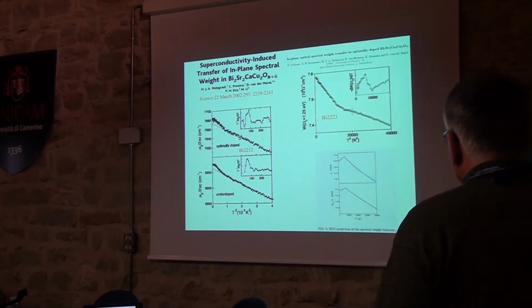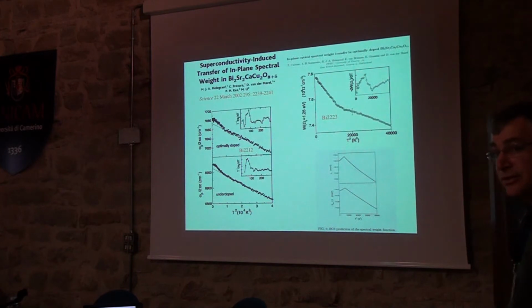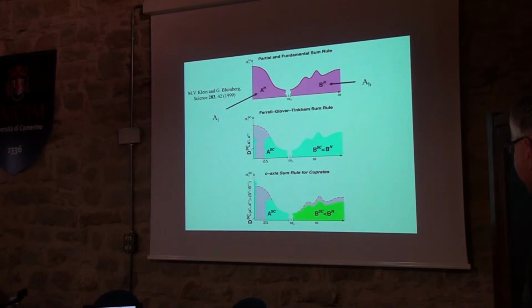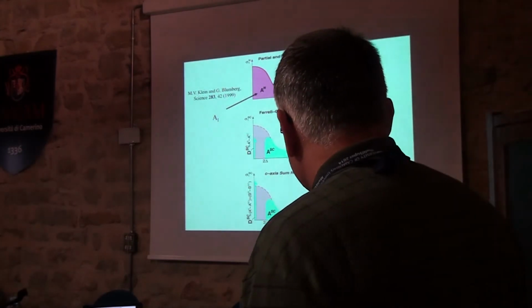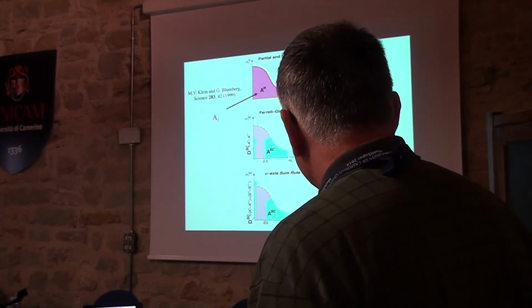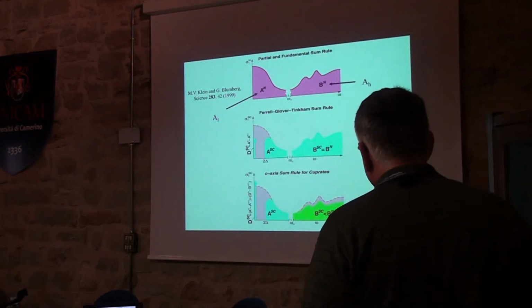So this experimental result is consistent with the ideas I just told you about coming from the dynamic Hubbard model. I'm not going to show you that explicitly because I don't have time, but here it is in a sketch done around that time, and it shows up as a violation of the optical sum rule. Okay, so this is for the c-axis, but we focused on the in-plane. So it's as if there's extra spectral weight out here, and that extra spectral weight loss is coming from the secondary orbital that I mentioned.